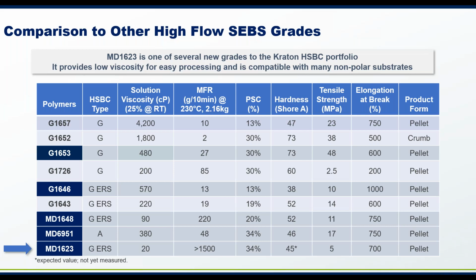This table here is a summary of the new high flow polymers compared to some classic and well-known Kraton G grades. And as you can see, the MD1623 has the lowest viscosity and the highest melt flow rate compared to the other high flow SEBS grades. Again, this allows for easy processing and also is compatible with many non-polar substrates. The table also demonstrates our design expertise to deliver many polymers with a variety of performance.